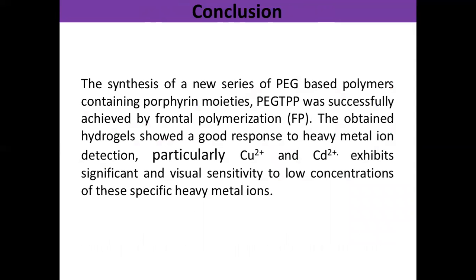In conclusion, the synthesis of a new series of PEG-based polymers containing porphyrin moieties, PEG-TPP, was successfully achieved by frontal polymerization. The obtained hydrogel showed a good response to heavy metal ion detection, particularly copper 2+ and cadmium 2+, exhibiting significant and visual sensitivity to low concentrations of these specific heavy metal ions.